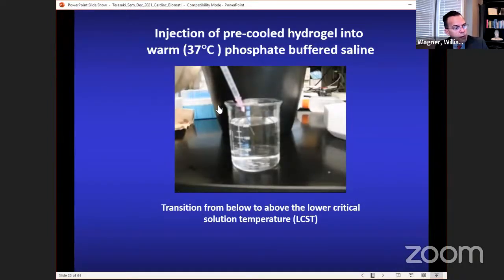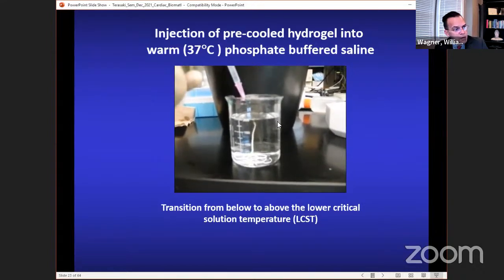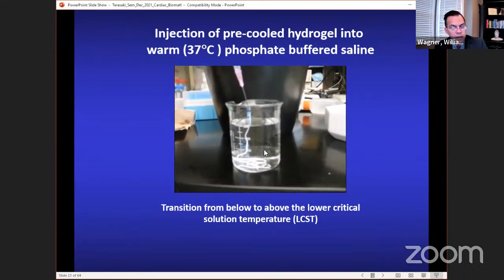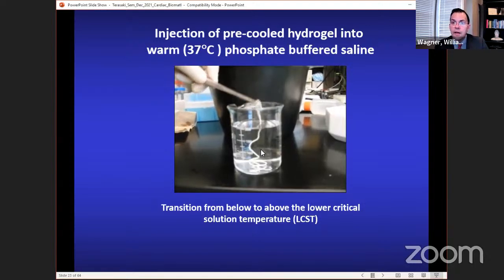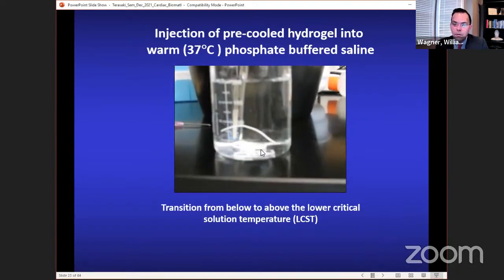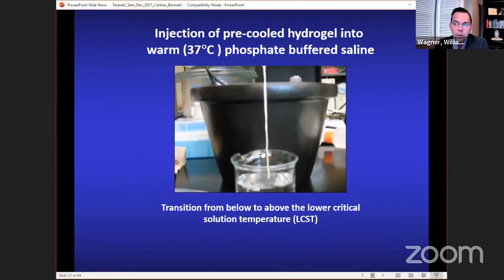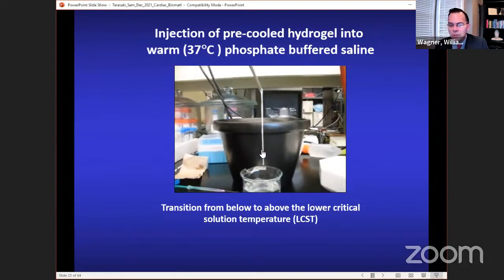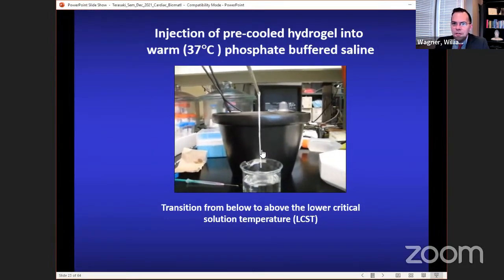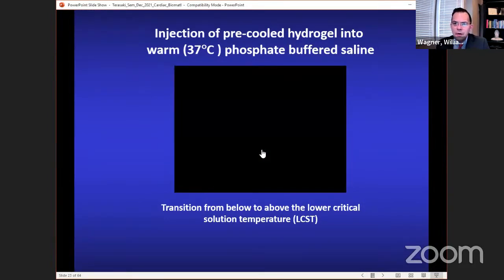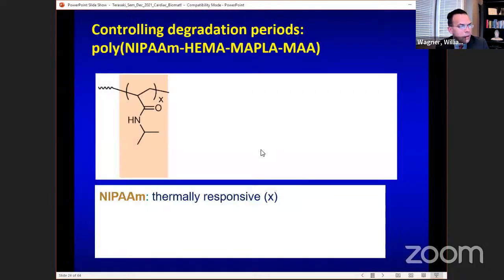Here's an example of one of those polymers in the syringe. You can see this is 37-degree saline. That's real time. So when you inject, it's doing that phase change quickly, which is what you need. Two minutes is too long. You can't do injections and then wait and hope it gels. You need it to gel quickly. Even with quick gelling, you're still going to have some regurgitation. So a little bit of regurg is okay, but too much is not good.